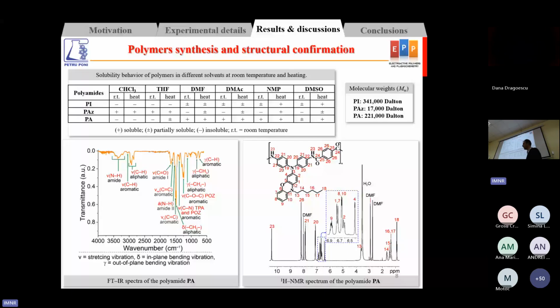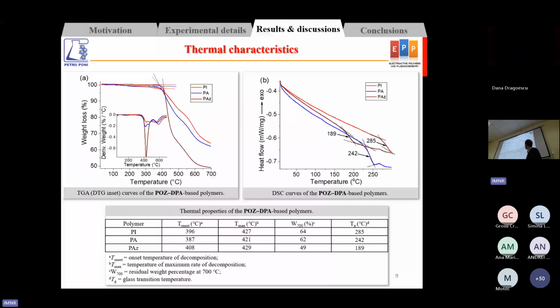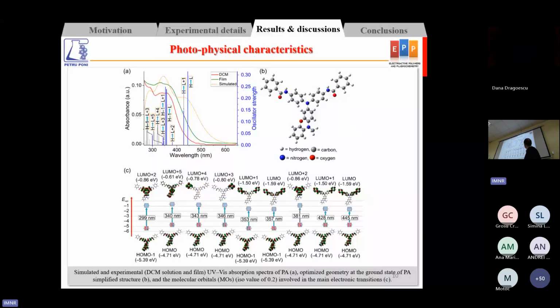Then we tested the thermal stability of the polymers so that we can prove that they meet the criteria for use in optoelectronic applications. The polymers showed good thermal stability and also high glass transition temperatures. We recommend them for use in optoelectronic applications. Since the polymers incorporate donor-acceptor moieties, we characterized them from an optical point of view.